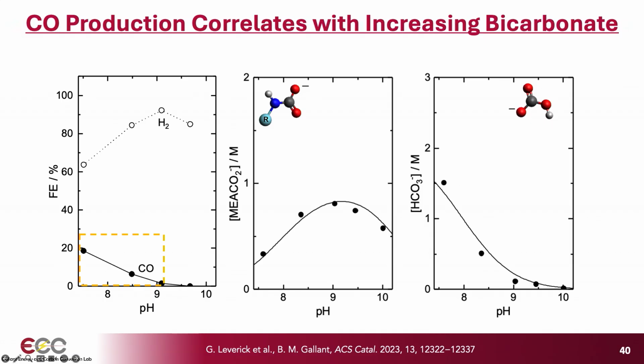In the middle graph, we have the carbamate concentration as a function of pH, and on the right-hand graph, we have bicarbonate. And so what's interesting here is that if you look at the range over which the CO selectivity is increasing, the carbamate has actually reached its maximum and is already decreasing by then. Okay, so we don't see a correlation between the carbamate concentration and CO. We do, however, see that over this region, that's where the bicarbonate hydrolysis reaction is occurring increasingly. And so we do see a pretty clear uptick in this that seems to correlate with CO selectivity.